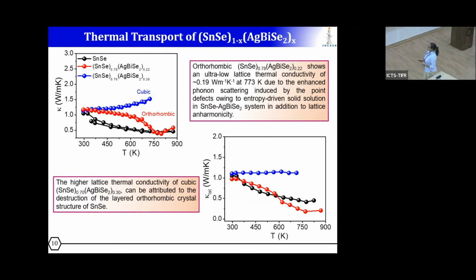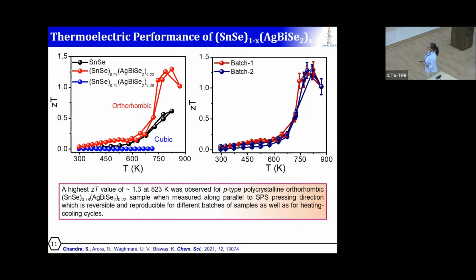On the other hand, if we look at the thermal conductivity of the cubic AgBiSe2 alloyed system, it is quite higher as compared to the pristine and the orthorhombic SnSe-AgBiSe2 alloyed system, which can be due to the destruction of the layered crystal structure of SnSe. So by combining these results, we have achieved a very high ZT of 1.3 in this 22% AgBiSe2 alloyed orthorhombic SnSe system, which is reproducible and reversible for both heating and cooling cycles.